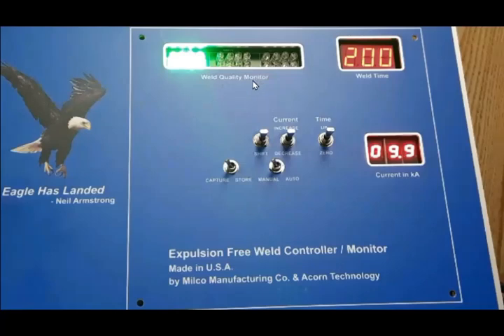Use the shaft and increase/decrease switch to adjust the current to 9.9 kA. Use the shaft and up/down to adjust the weld time to 200 milliseconds. Put the capture/store switch in capture position and the manual/auto switch in manual position. Make a few welds and peel them. If you are satisfied with the nugget size, switch to store and auto. You have programmed to weld at this current.